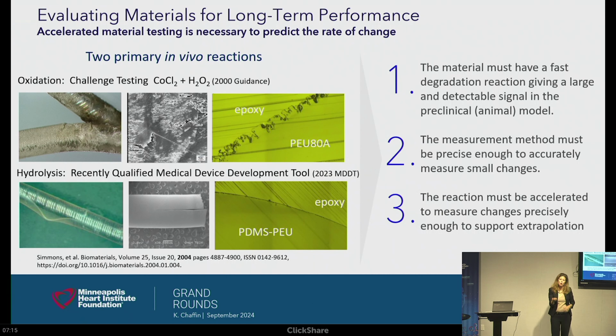But hydrolysis is a bulk reaction. So the water permeates the bulk of that polymer first and reacts with every single bond, as opposed to macrophages that sit on the surface and spit out their debris, their superoxides, and those oxides are very, very reactive, and they react before they diffuse in. Water is not that reactive, but there's enough reaction when we're talking about 10 years, 15 years, 20 years, that it reacts in the bulk. And so we tend to see smooth surfaces, and we tend to see bulk failure because we don't have good material sitting underneath to support that mechanical load that we talked about.